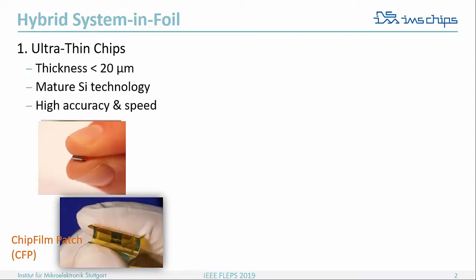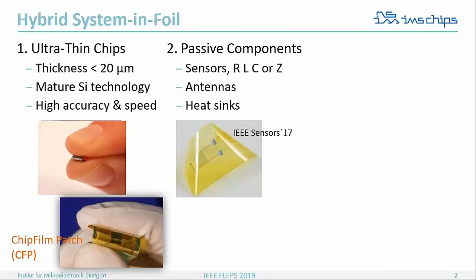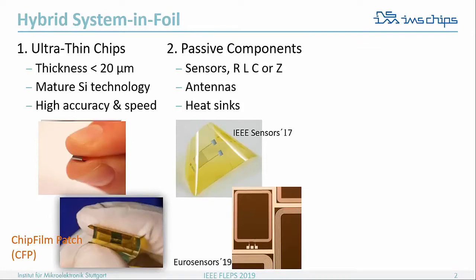And on the same platform, this chip film patch technology, we can also do some sensors. So resistive, capacitive, or electrochemical sensors. We have tried many sensors. So one example is this humidity sensor. It's a simple interdigitated capacitor where relative permittivity changes upon moisture absorption. And also some antennas for NFC, the well-known 13.56 megahertz, next to this thin silicon.